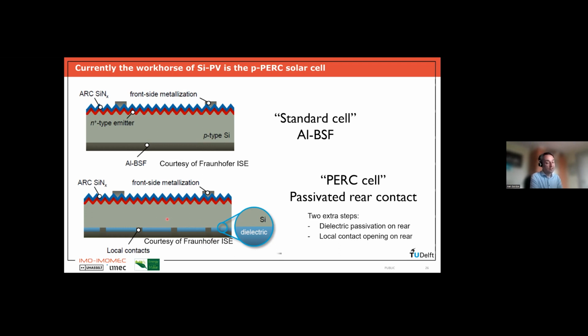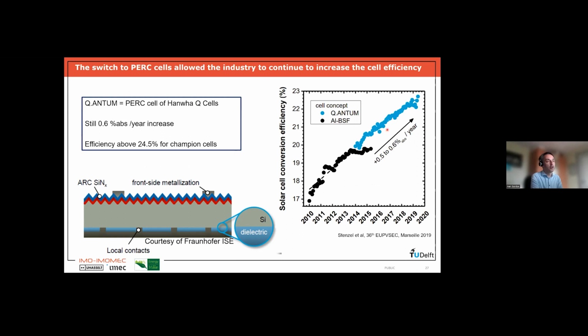Of course, this cell structure is a little bit more complicated, and to produce it in the industry, you need 2 extra steps. You need to grow the passivation layer or deposit it somehow on the rear surface. And then you have to make these local contact openings through the dielectric, which is typically done by laser. So that means you need extra equipment, you need 2 extra steps in your production process. So you will have a higher cost, but the higher cost is no problem because we also have a much higher efficiency. And this is shown again here in the data of the Hanwha Q Cells factory.